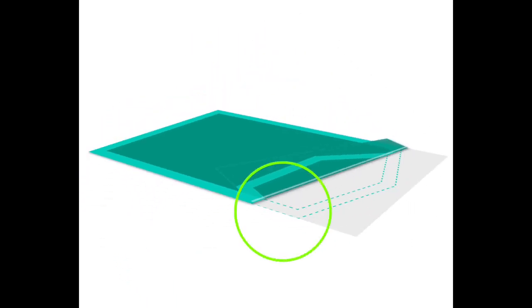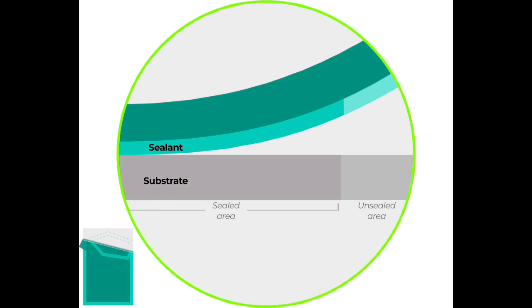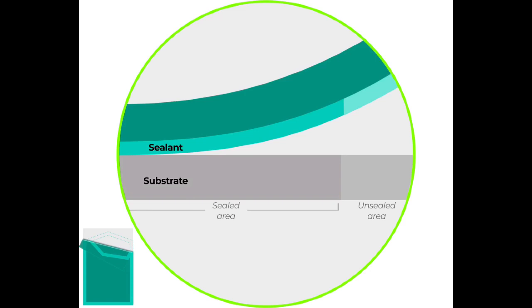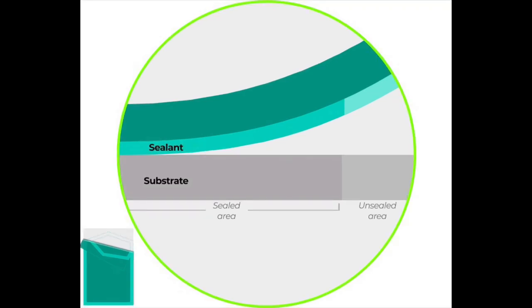We can talk a little about the mechanics of the different peel mechanisms. I think most people are familiar with polyester polyethylene seals to uncoated Tyvek, which would fall in the adhesive peel category. If we could pull up the animation and look at the adhesive peel mechanism, the light green line represents the film sealant, and the gray area represents the substrate to which it is sealed. In this case, it would be the Tyvek. As the film is peeling, it leaves both surfaces pretty much in the exact same state they were in before they were sealed. There's no transfer of any molecules between the surfaces. It's strictly just separating the two.